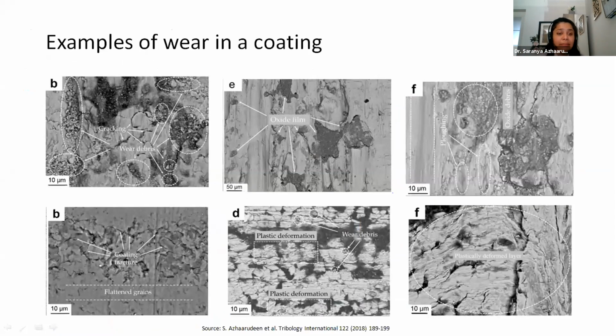So this is basically my paper, because I was working on manganese phosphate coatings. In these coatings, we were checking the wear of the surface after use in a SEM, scanning electron microscope. You can see there are lots and lots of different forms of wear in a single surface. If you see, there are forms of cracking. In the first picture, there is a lot of wear debris. Wear debris means the wastage from the cracking of the materials. And in the second picture, there is a lot of oxide film formation. And in the third picture, you can see there is a lot of ploughing.